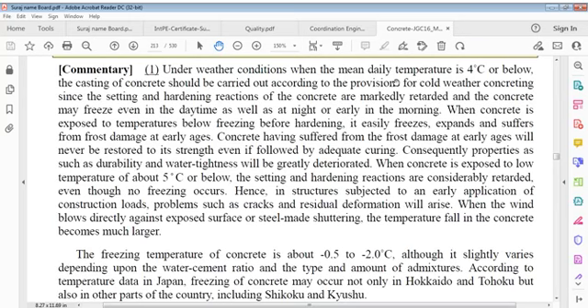When concrete is exposed to temperature below freezing before hardening, it easily freezes, expands and suffers from frost damage at early ages. Concrete having suffered from frost damage at early ages shall never be restored to its strength even if followed by adequate curing. Consequently, properties such as durability and water tightness shall be greatly deteriorated.